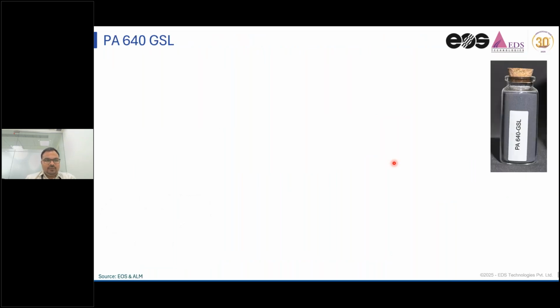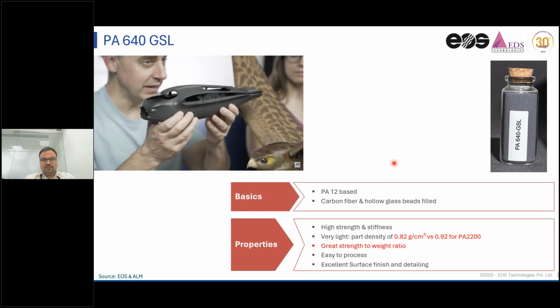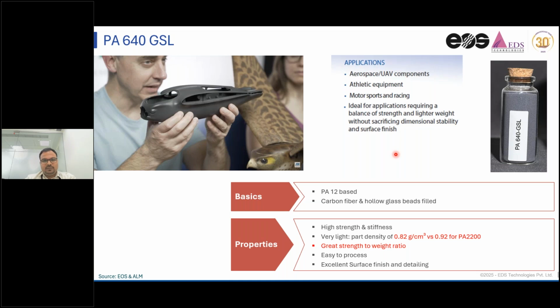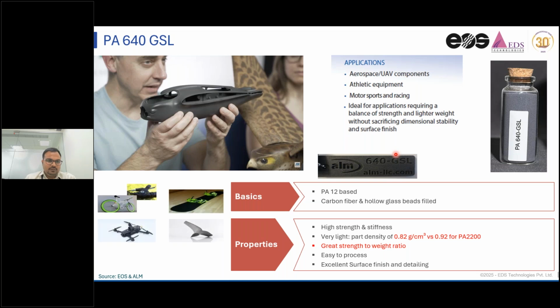We have another carbon fiber material, which is PA640 GSL. It is a PA12 based material again, nylon 12, and it's a mixture of carbon fiber and hollow glass beads filled. And the best part of this material is with the same amount of mechanical strength, it is 10% lighter than the other available plastic material in the market. So it offers another 10% of advantage to your drone design, and you can imagine more endurance of your drone when it is running because the flight time is increased and strength to weight ratio is also increased with it. It is easy to process and it gives excellent surface finish. It is available in matte gray color and matte black gray color, I would say, in appearance.